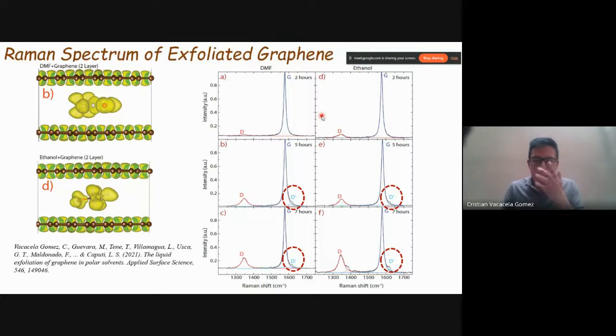That is the goal, and many people continue working on the potential applications of these few layer graphene samples. For example, we just focus on the D and G band regions. After 2 hours of sonication, what happened? Of course, we can observe the D band and the G band. After 2, 5, and 7 hours of sonication, independent of whether we use dimethylformamide or ethanol, we can see the presence of the D peak. If you remember our previous explanations, it is the presence of defects.